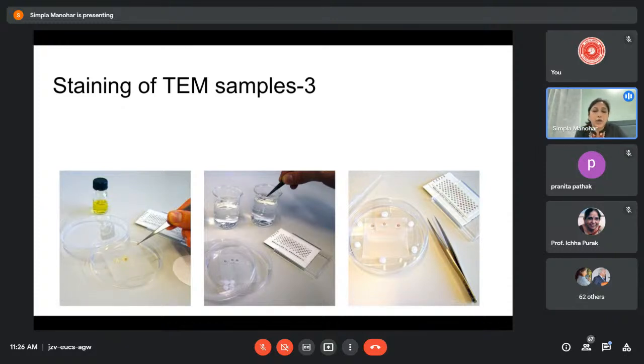After that, again, we take lead citrate and put it in drops, and you can see we have added sodium hydroxide pellets on the side. What sodium hydroxide does is it sucks up all the carbon dioxide which is around so that lead citrate does not precipitate. Again, we leave the grids on the lead citrate for some time, and then we can wash.